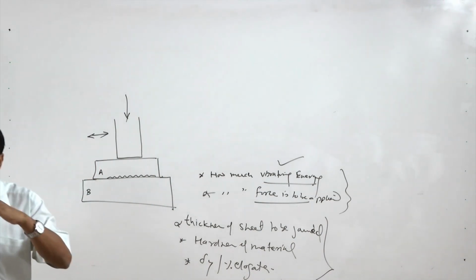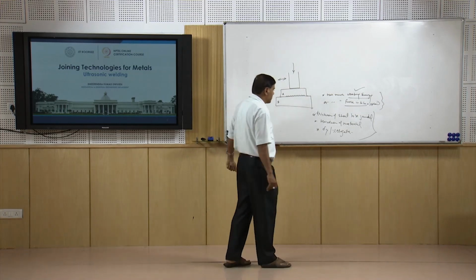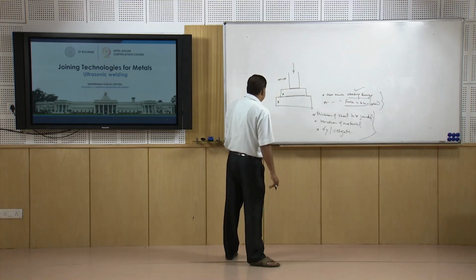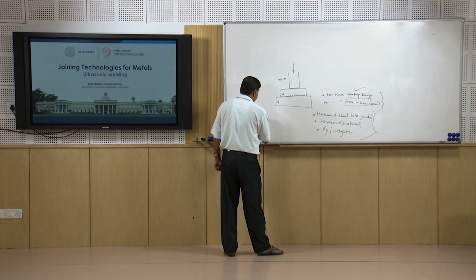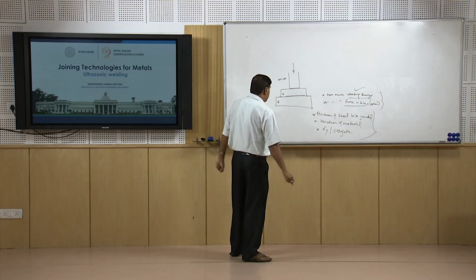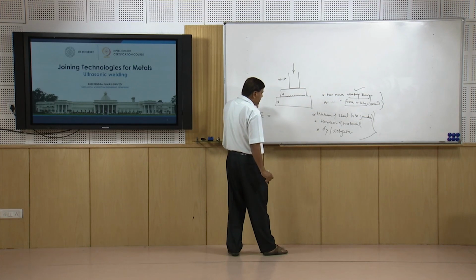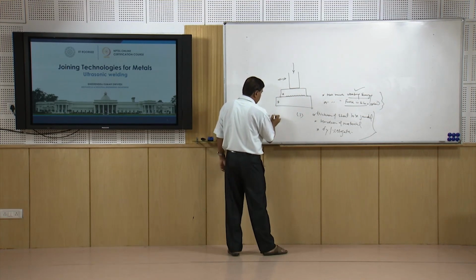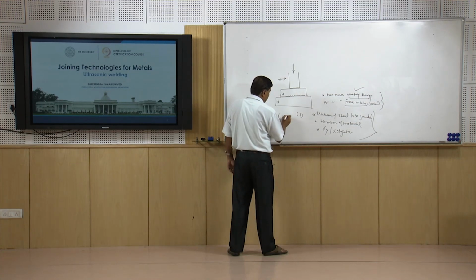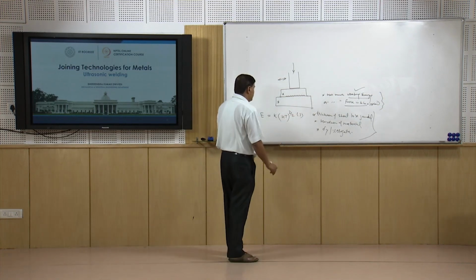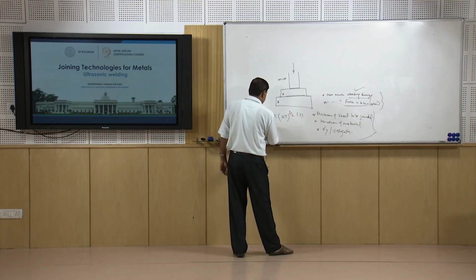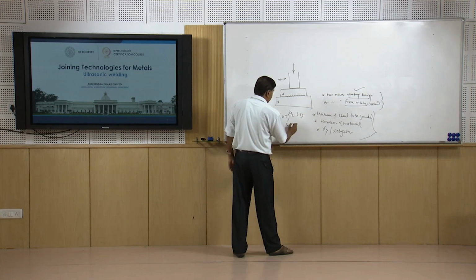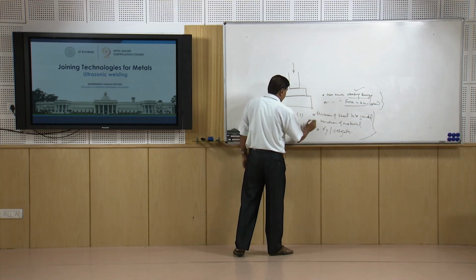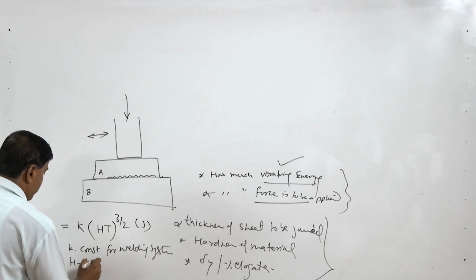So, since the thickness and the factor governing the ability for plastic flow influence the success of the process significantly, these two parameters significantly determine the energy which is required for development of the ultrasonic joints, and the vibratory energy to be supplied, say in joules, is found to be a function of K multiplied by H into T raised to the power 3/2. So, this is the energy in joules, K is a constant for the welding system being used for development of the weld joint, and H is the Vickers hardness of the material which is being joined.